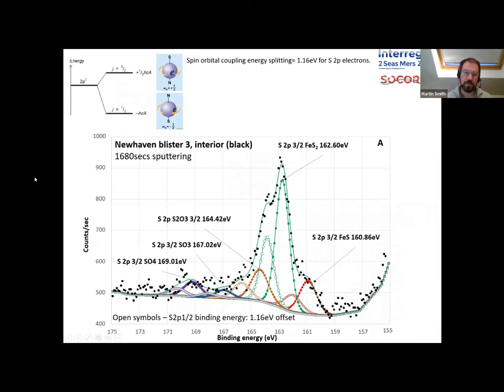So this is a sample from Newhaven Harbour taken as part of the SOCOR project. And this is a sulfur 2p electron binding energy spectra. What I've got here, I've plotted this out in detail. So the black points are actual measurements. The green solid line coming across the whole spectrum there is the fitted curve. And the individual peaks are the peaks we fitted to deconvolute that spectrum.